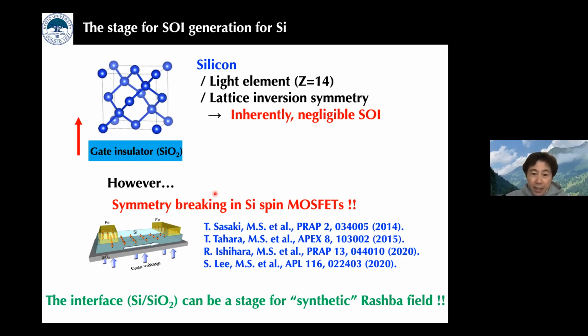So luckily, we have been investigating the spin transport physics in silicon by fabricating silicon spin MOSFETs. And we have a sufficient accumulation of knowledge about the spin transport physics. So our motivation was: what happens when we apply a strong gate electric field to the silicon channel via the SiO2 gate insulator? So we expected the formation of a synthetic Rashba field.